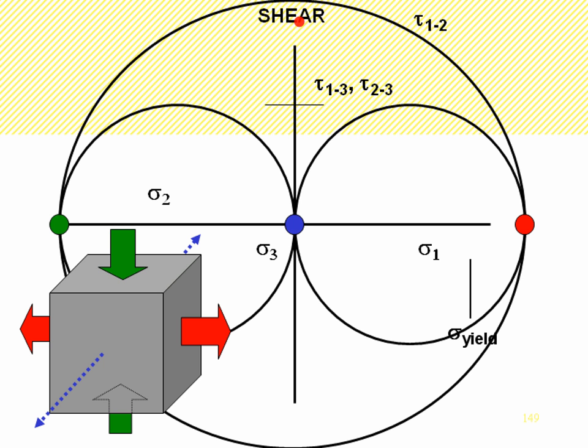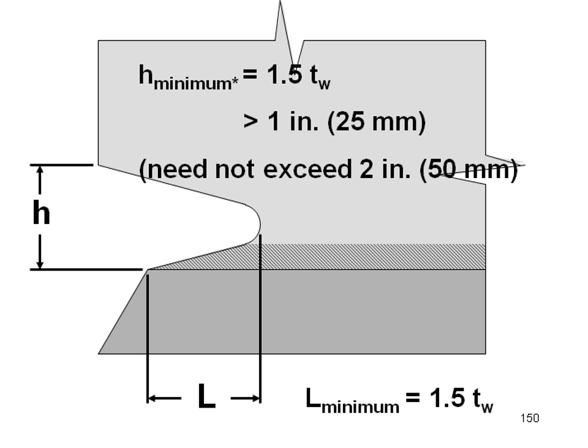Now, that's part of the logic that was imposed when the weld access hole sizes were increased back in the mid-'80s. You don't need an access hole this big for access for welding. These bigger access holes were to preclude the interaction of the residual stresses from the groove weld of the web and the groove weld of the flange.